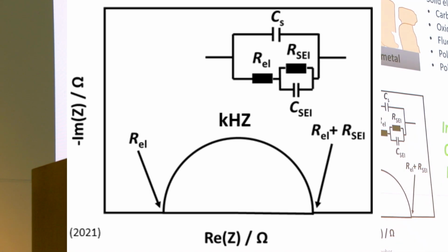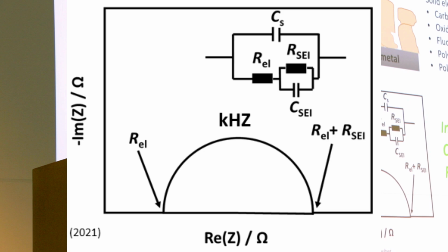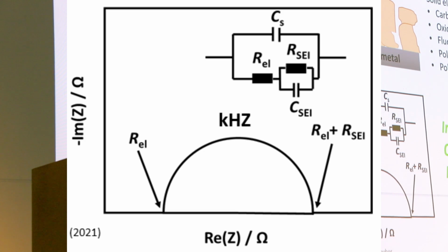Or we end up already with a porous film, which can be, again, a native oxide film, or anything that decomposes the very instant we contact our metal with a liquid electrolyte. And then we have an anion or solvent diffusion through these pores, and then a contact at the liquid-solid interface where the growth happens. And in this case, my SEI is drawn as one material, but we of course know it's actually a very complicated, nanostructured, inorganic, organic material in which we don't even really know if the specific phases are crystalline or amorphous. So we are still interested in knowing this.